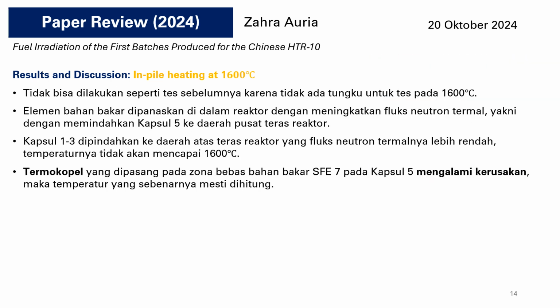Moving to the results and discussion for in-pile heating at 1600 degrees Celsius. Actually, this test cannot be done like the prior test because there is no furnace for the 1600 test. So we have to increase the thermal neutron flux by moving capsule 5 to the center region of the reactor core. Meanwhile, the other capsules were moved to the upper region of the reactor core that has less thermal neutron flux, so the temperature could not reach 1600 degrees Celsius.